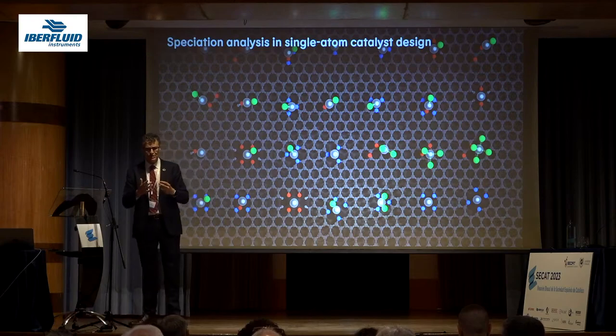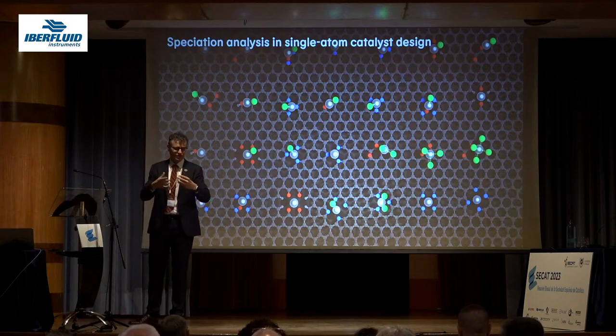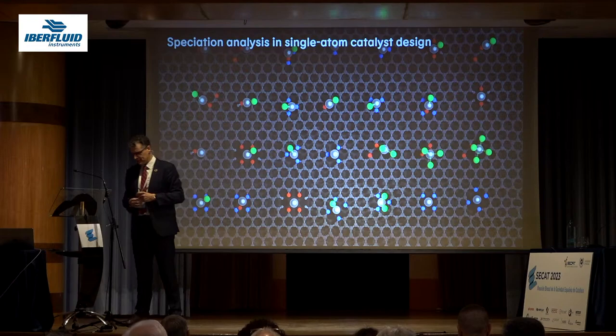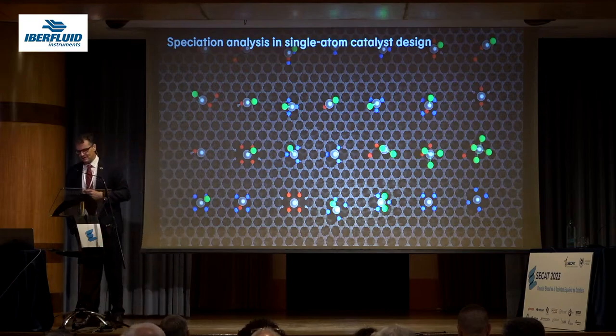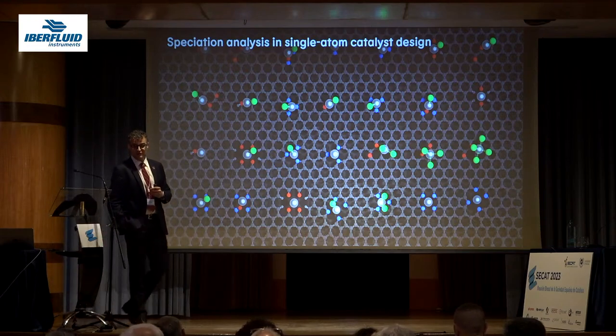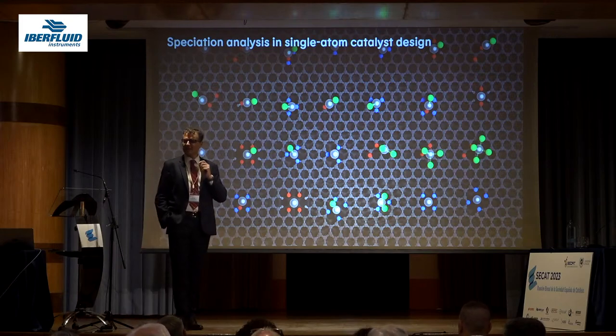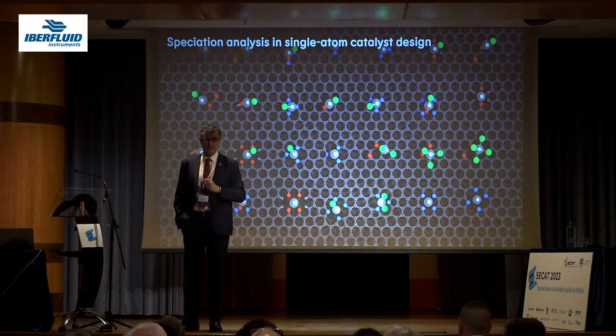We are quite busy on this at this moment. I'm not able to share the final results because we are still interpreting data, but our tentative assignment of the nanostructure of the platinum single atom that works is one that has 2 ligands of chlorine under reaction conditions, and it is attached to 2 oxygen functionalities of the carbon. A very specific site. Not every site is equally active, as you can imagine.